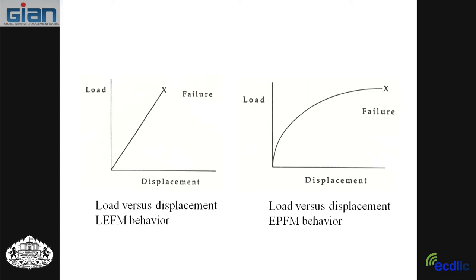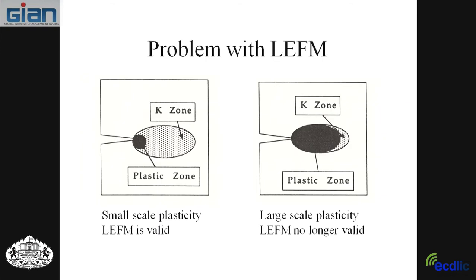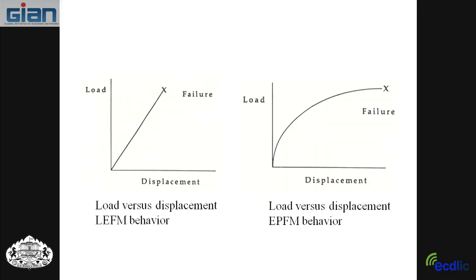So here's another way to tell that you have too much plasticity. If you have load and you measure displacement somewhere on the specimen, and you get essentially a straight line, then you know it's essentially linear elastic behavior, so you know you're in this condition, small plastic zone. If you're loading and you get grossly nonlinear load and displacement, then you have lost the linear elastic behavior, and we often call that elastic plastic fracture behavior. So another way to tell besides the plastic zone is load and displacement. Almost all the tests have load and displacement measurement built into the test method, so you can see if you essentially have this or essentially have that.